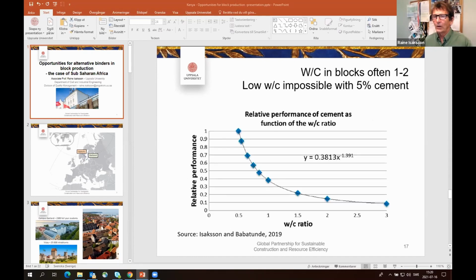Now this is a curve I think you have seen, adapted. So the water cement ratio, and I've taken typical concrete with 0.5 water cement ratio as the reference, as number 1. But what happens when we have 5% cement? Now if you think of it, we might have to add up to 10% of water in order to get the sand matrix to compact properly. If I add 10% and I have 5% of cement, we end up with a water cement ratio of 2, or maybe only 1.5, which means that we only use about 20% of the potential strength of the cement.